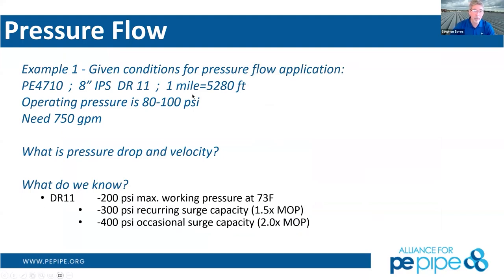So we know right off the bat, without even going to the software, that DR11 has a max pressure rating of 200 PSI at 73 degrees. It's also going to have 1.5 times that in your recurring surge capacity. That's up to 300 PSI. So 200 plus another 100 gives you 300 PSI surge capacity on an everyday basis, 10 million cycles, 55 cycles a day for 100 years. And occasional surges, which is going to be a few million cycles over 100 years, at 400 PSI, double the pressure class or pressure rating. So we know that just off the bat.